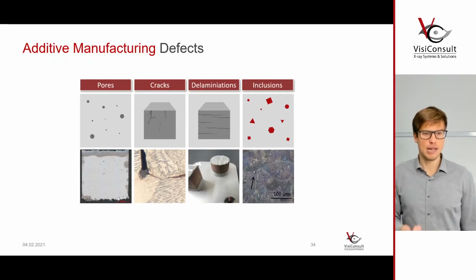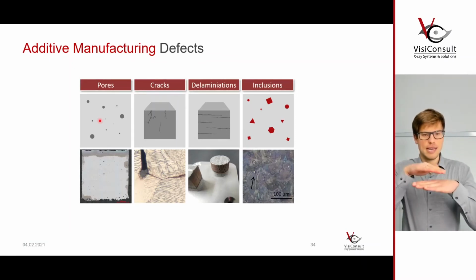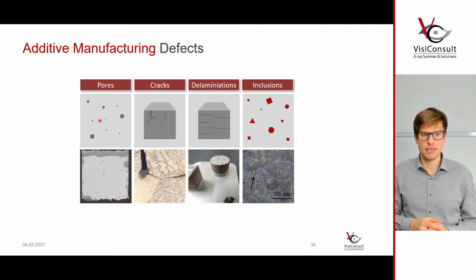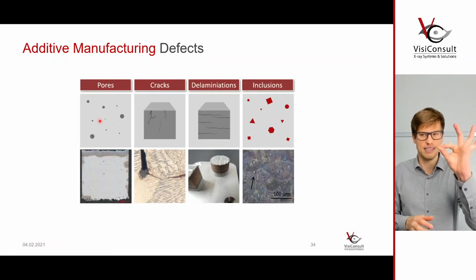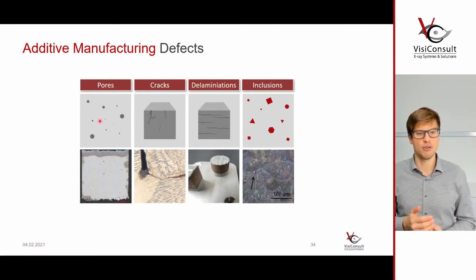In casting and welding, these are all technologies that have been known for years, maybe for hundreds of years. So we kind of know how they act. We kind of know how pores look like. They are typically round in castings. We know how cracks look, how they start. They come from crack kernels, maybe some residual stress on the part. We know these defects, but the challenge is in additive manufacturing they look different because due to the layered approach, porosities are not round anymore necessarily. They can be, they can have edges. They can look like this. They can have a starting point for a kernel for a crack.